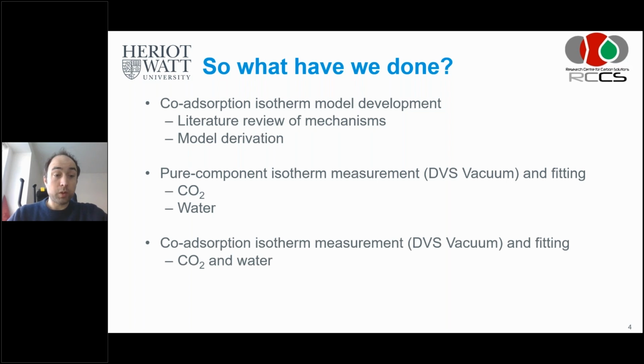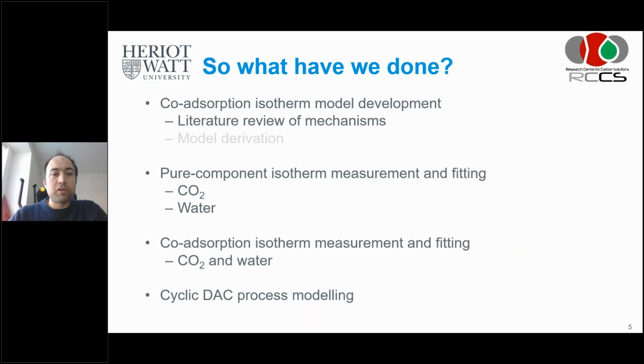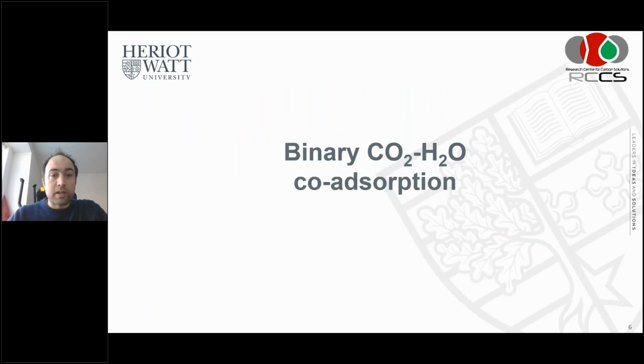And then we went on to do co-adsorption isotherm measurements, also with the DVS vacuum, and fitted again CO2 and water. The reason why we acquired the DVS vacuum is that, under certain assumptions and in certain conditions, it allows you to do these co-adsorption measurements and to differentiate between how much CO2 and water is adsorbed. And then finally, what we did is DAC, direct air capture process modeling. So we modeled cyclic direct air capture processes to understand the performance of these processes and also to see how we could optimize them. Now, I will leave the model derivation for what it is. I have some in the back of the slides for whoever is interested, but it's also published in our 2021 paper in Energy and Environmental Science. But I'll focus on the other elements.